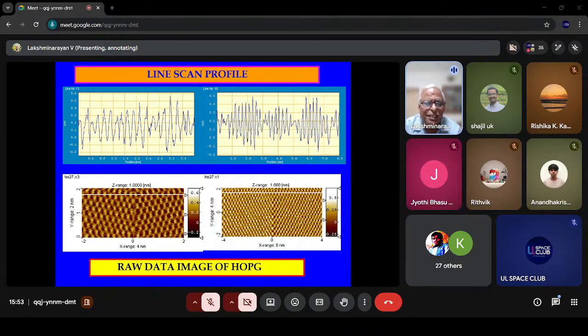And so this is the first image about which I am always excited, of highly oriented pyrolytic graphite. So these are all carbon atoms. I will not go into too much detail about whether this is a carbon atom or electron density, because strictly speaking, these are what's called a local density of states. There is a subtle difference between the two, but you can actually see these carbon atoms. This is during the forward scan, and this during the reverse, and you can see the hexagonal pattern here.